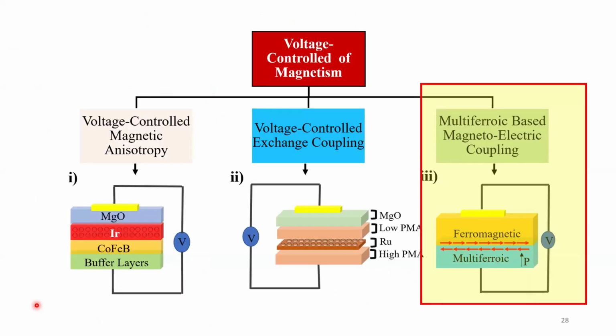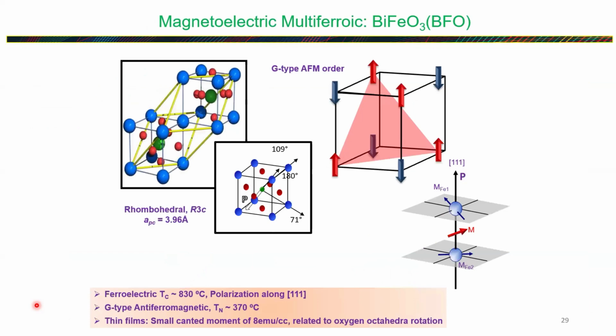Mechanism, second one. Now, third one is the multiferroic based magnetoelectric coupling. Okay, so here, I'm introducing a material called magnetoelectric multiferroics, which is bismuth iron oxide, BFO. Bismuth iron oxide has two ferroic orders. It is basically ferroelectric and it is also antiferromagnetic. So it's a G-type antiferromagnet, and it is ferroelectric with a polarization of around 90 microcoulomb per centimeter squared, and the polarization vector is in the 111 direction.